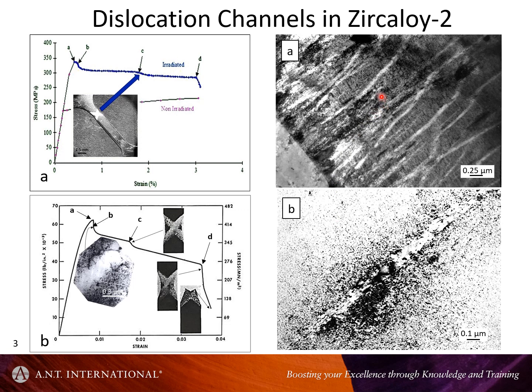So in this case, this is zircaloy 2 irradiated at 60 degrees centigrade. You've got a lot of channels running into a boundary here. We'll talk about the interaction of channels with boundaries, but just make a note that there's nothing happening at the boundary. There's no cracks forming or anything like that. But also note that the channels are not necessarily planar, and they're varying in width, and there's a lot of complexity there when it comes to cross slip and moving on to different, on a more macroscopic or less microscopic scale, a non-planar kind of clearing or channel morphology.